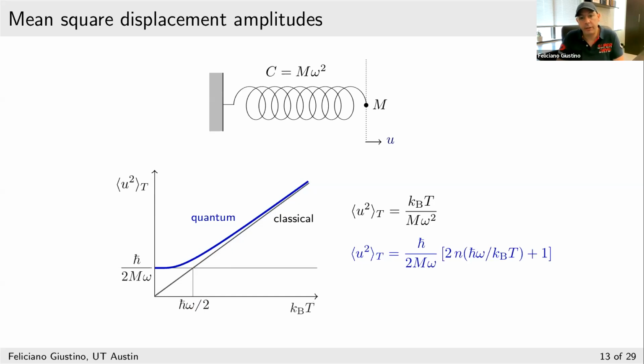If you're considering, on the other hand, something like graphene, typical phonon energy is of the order of 200 millielectronvolts. So this is going to be 100 millielectronvolts. So room temperature is approximately here. So in the case of graphene, using classical dynamics is not going to cut it, okay? So that's a very simple way to keep in mind when you need to use certain approximations.